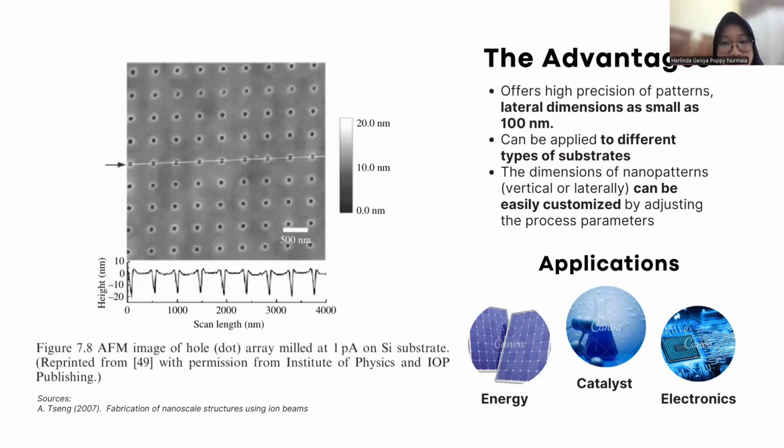Okay, next we have an AFM, or atomic force microscopy, scan of a surface with nanopatterns. From this scan, we can see the consistent spacing between the nanopatterns that indicates effective radiation grafting and ensures uniform structure formation of nanoparticles.